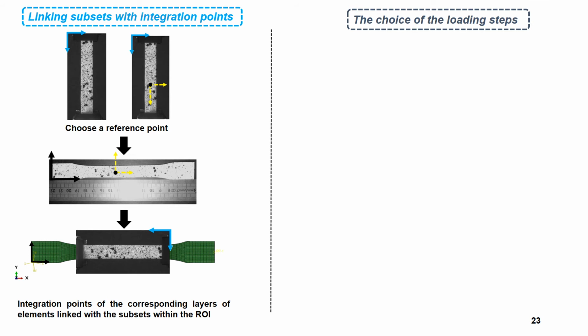First, we perform a linking procedure between the subsets in the reference snapshot and the undeformed mesh. Here, the density of subsets is higher than the integration points, so we decided to reduce the data size to fit the number of integration points by linking each one to the neighbor subsets.